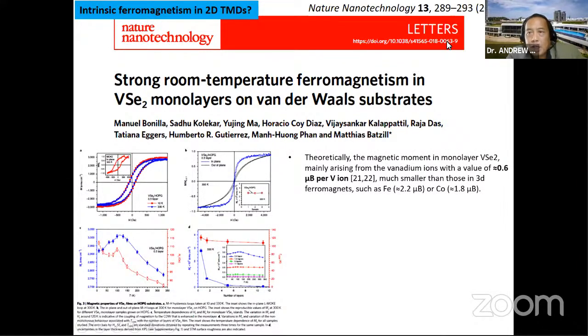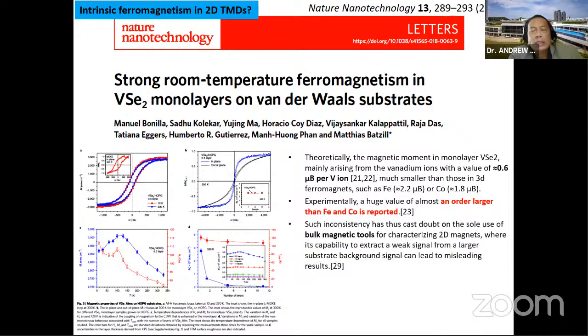But let me just highlight here some key points of this paper. So before this paper was published, theorists had calculated the magnetic moment in 2D vanadium diselenide, and it arises mainly from the vanadium ions, as we would expect, and it has a value of about 0.6 Bohr magneton per ion, which is much smaller than that of the traditional 3D ferromagnets like iron or cobalt. But their paper actually reported a huge value, an order of magnitude larger. So this raises some questions. Either the theory is wrong, or something in the explanation of the experiment is not quite right.